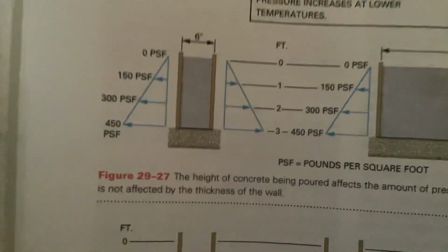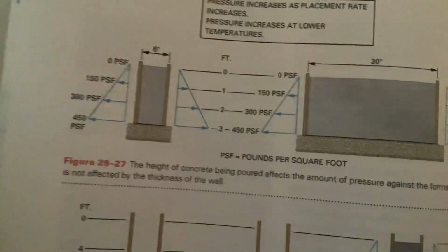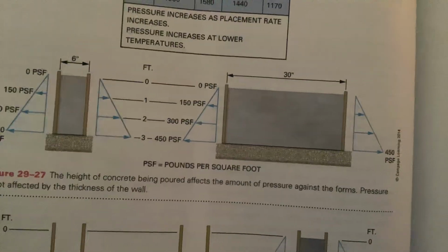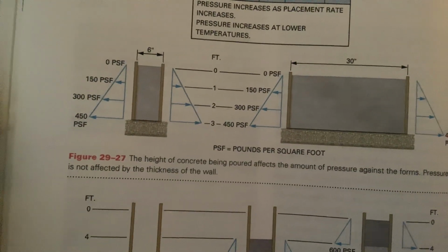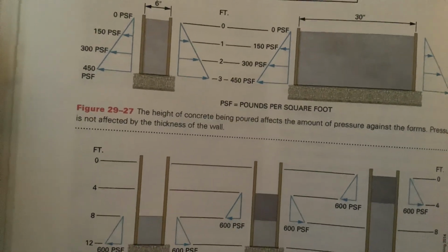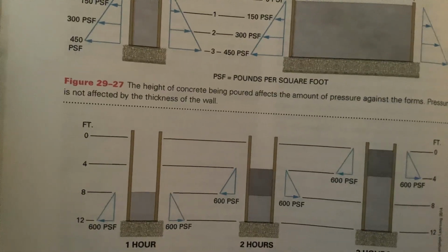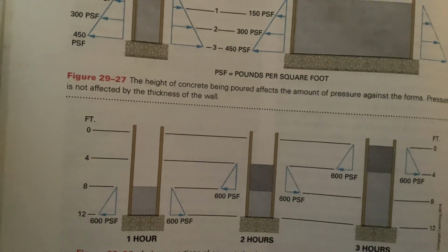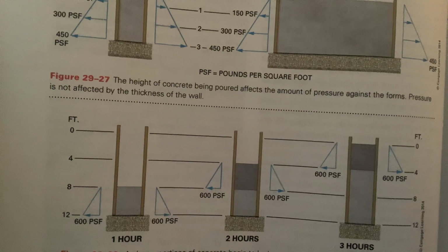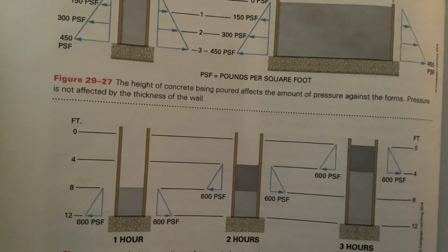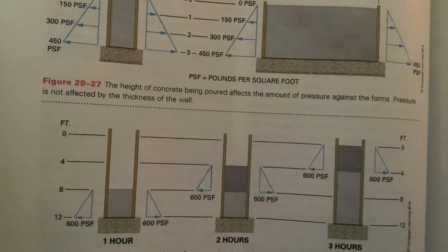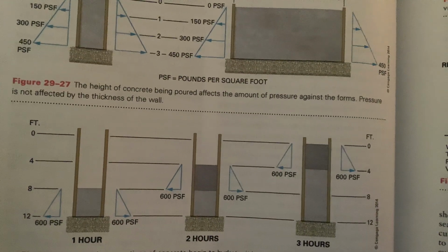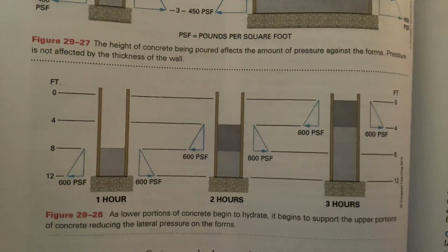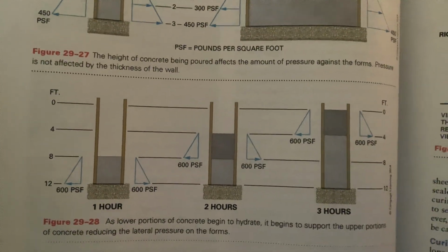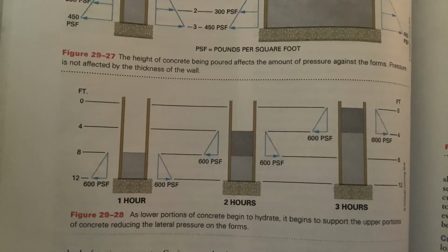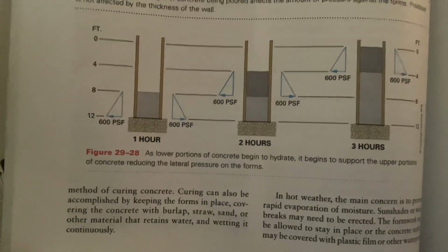The height of concrete being poured affects the amount of pressure against the forms. Pressure is not affected by the thickness of the wall. 600 psf, 1 hour, 12 feet, 2 hours, 3 hours. As lower portions of concrete begin to hydrate, it begins to support the upper portions of concrete, reducing the lateral pressure on the forms.